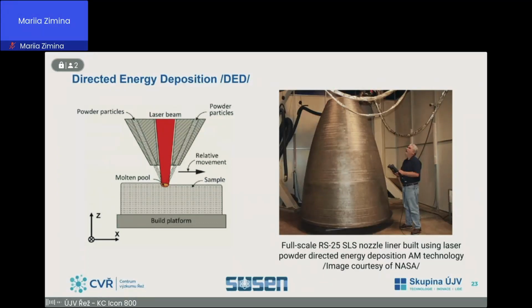Technology shortcomings. One limitation of the directed energy deposition process is that it can usually be used only in welding position, horizontal from above, and the potential to create unwanted defects is similar to welding.